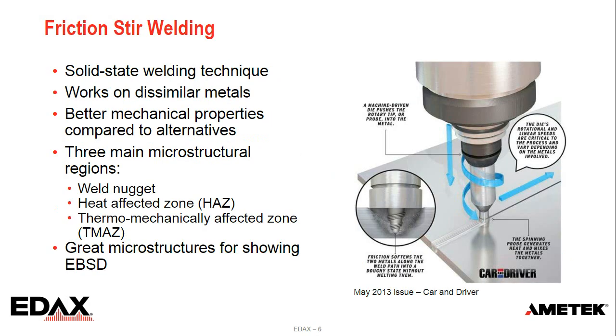So to start, I wanted to talk about some friction stir welding and show some examples from a steel sample. If you're not familiar with friction stir welding, it's a solid state welding technique. It's of interest for steels because it works with dissimilar metals, can be used to weld steel to aluminum, and the mechanical properties come out better compared to other alternative welding techniques. There are different microstructural regions, and they make really pretty pictures for EBSD, as you'll see. You can see a little diagram here of how this goes, but again, the tool is pushed into the metal that's being joined. It stirs around, and the friction and the heat there creates a doughy type structure. It's a little hard to read the text on here. So it mixes things without melting. It's a solid state technique. And this is from Car and Driver magazine that covered friction stir welding a few years ago.